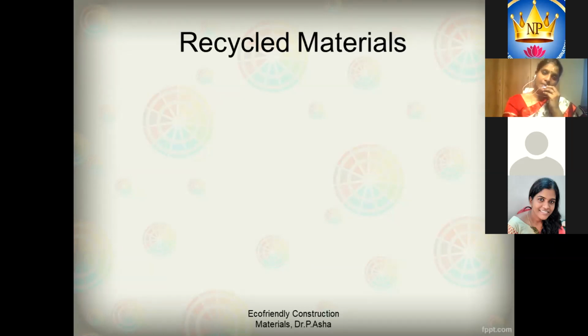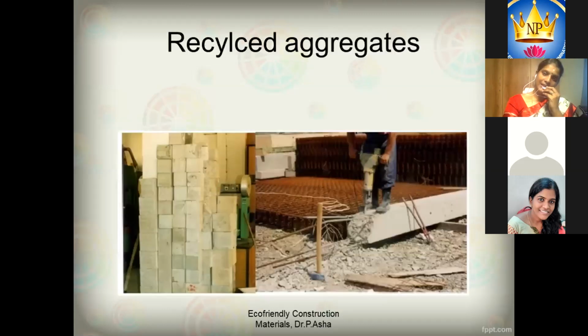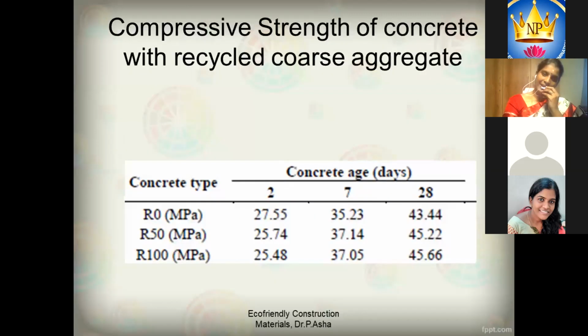So you can use the demolished concrete as recycled aggregates in the concrete. Researchers have already worked in this area, and they have found that the strength of recycled aggregate concrete is comparable or sometimes even higher than conventional concrete. Conventional concrete is 43.44 MPa, whereas the recycled aggregate concrete has 45.22. Even if you completely replace the coarse aggregates with recycled aggregates, the strength is about 45 MPa. Similarly, the wear resistance is also comparatively better than that of conventional concrete.